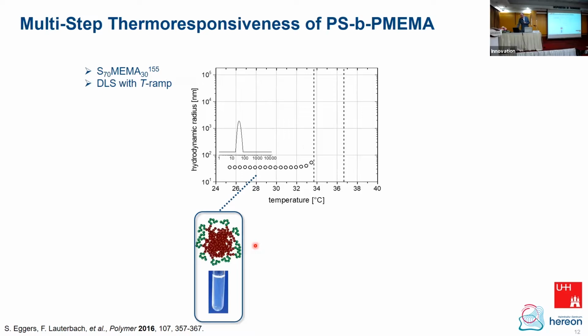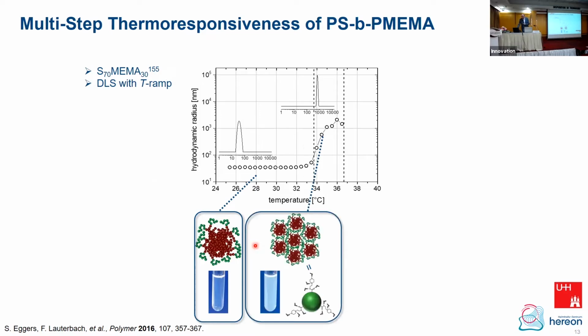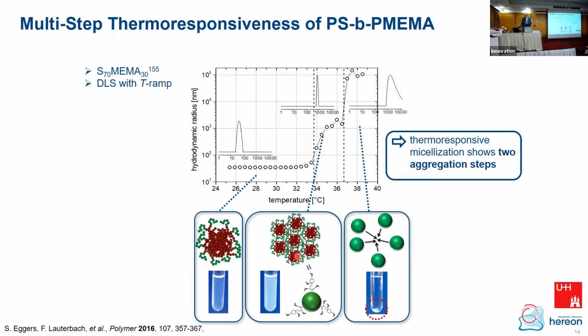Okay, here is just a temperature ramp of DLS. So we see here the analysis of the hydrodynamic radius as a function of temperature, and at different temperatures. And you see also the glass tubes with a micellar solution at low temperature or at room temperature, and then at higher temperature above the LCST, or above the cloud point of the corona block. These micelles aggregate together, and at slightly higher temperatures, the aggregates aggregate more together, and you get really a precipitation in your glass tube.